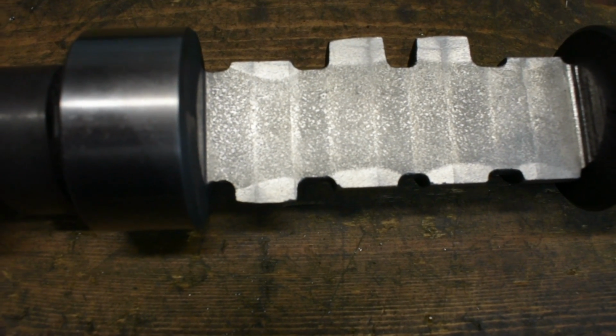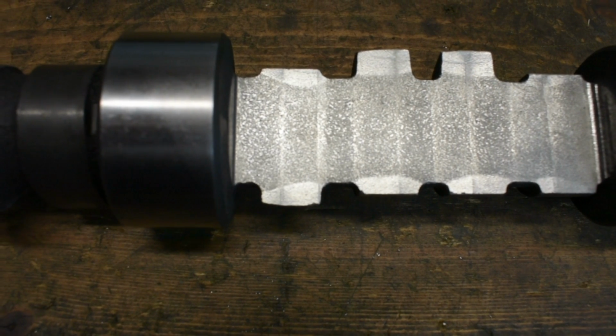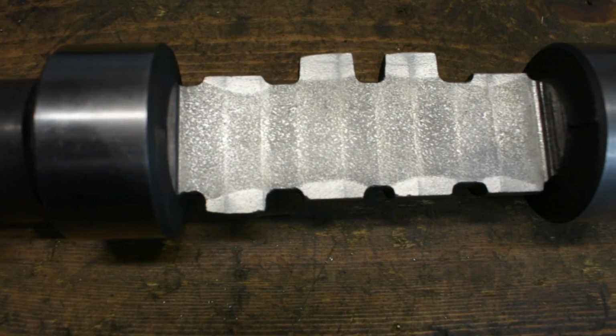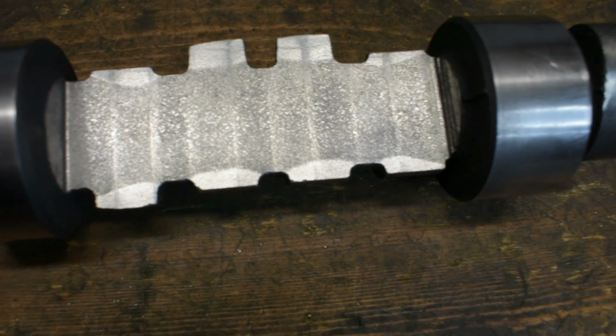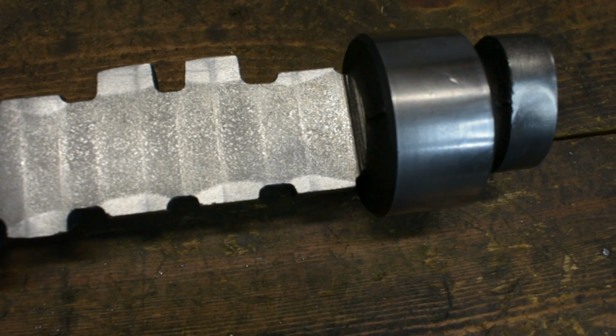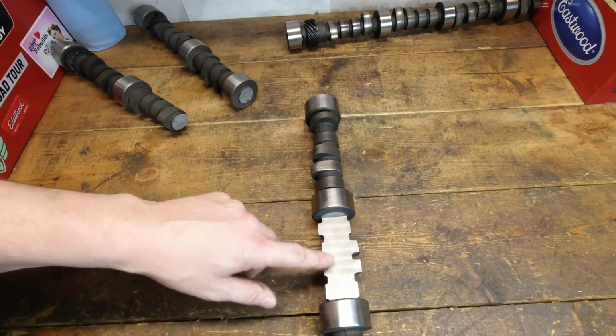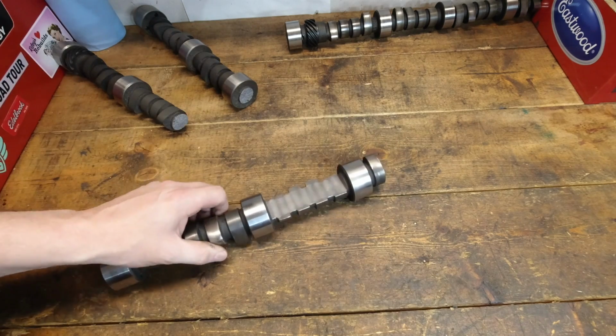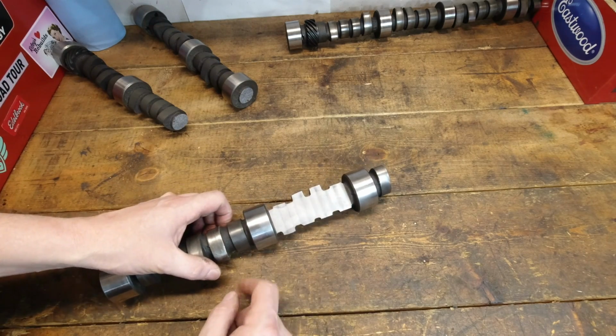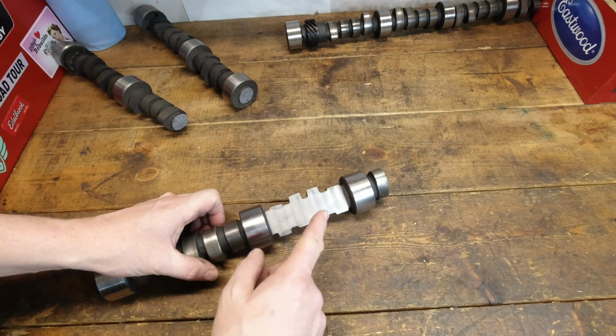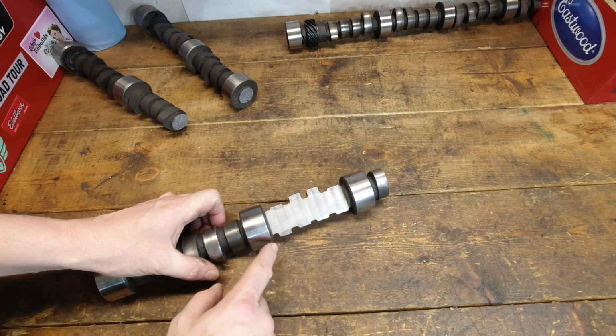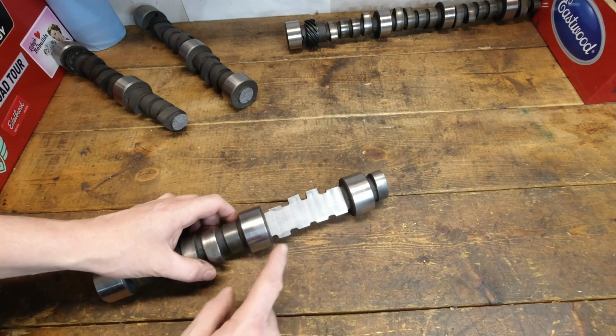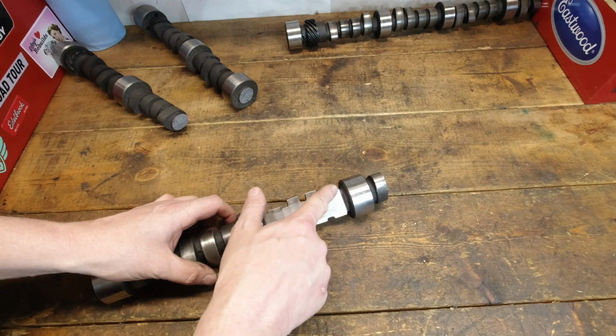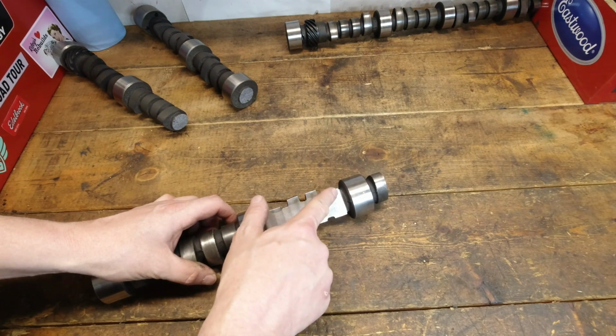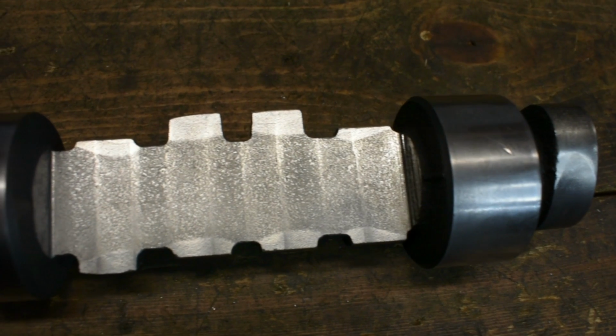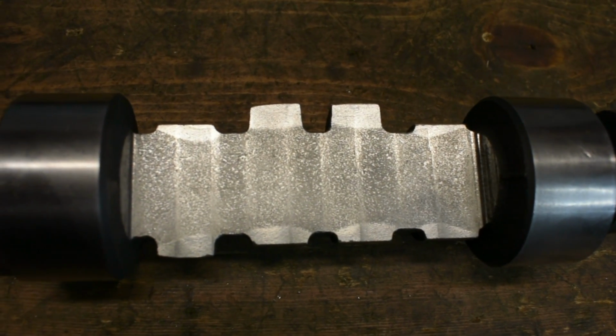And I think that's what most people just assume, that when it's heat treated, it means it's heat treated to a certain depth or all the way through, which in this case on a cast cam core is not true. But you can see where they can run into those issues. You get into the edges here, and if you're not careful with how you grind that camshaft, you could get into the heat treat fairly quickly. If you get into the heat treat and you grind that cam very low or in an area where it's going to wear down, you could get into this softer material.